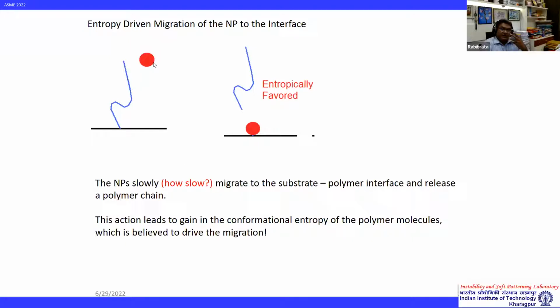So this particle is within the polymer matrix. They migrate to the substrate and release a polymer chain. And eventually they change in situ the wetting property. Now the question to ask is, why do they migrate? Well, it turns out there is probably an entropic driving force, because a polymer chain that is attached to the surface is actually quite restricted in terms of its conformational entropy. So if a particle migrates to the substrate surface or interface, gets attached and simultaneously releases a polymer chain, there is a gain in the conformational entropy of the polymer chain. So this is considered to be the driving force.